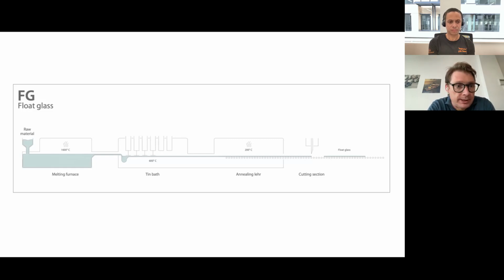So they're continually producing this ribbon of glass, which is produced by melting the component materials in a furnace at 1600 degrees. And to enable that float process, which was developed by Pilkingtons, it floats on a tin bath, so it's molten tin, and it gives it that smooth underside, and with the force of gravity, that gives it its surface quality on the other side. And then that's cut on the final section of the float line into transportable panels. And typically in the UK, across the world there, a jumbo sheet is 6 meters by 3 meters.